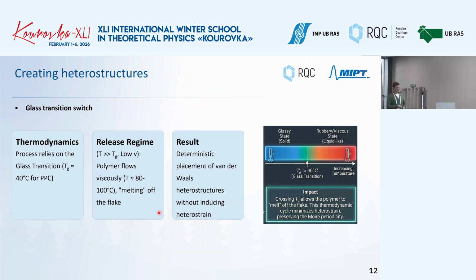And just to create these heterostructures, we discussed this stamp, where the polymer might put things down or pick them up, and then you need the so-called glass transition of this polymer. You change the temperature of your polymer, and at some point it is in the solid state and can stick, and then you can heat it up, increase the temperature, go over the glass transition, and then the polymer melts off the flake, and you can put your flake in your desired position.